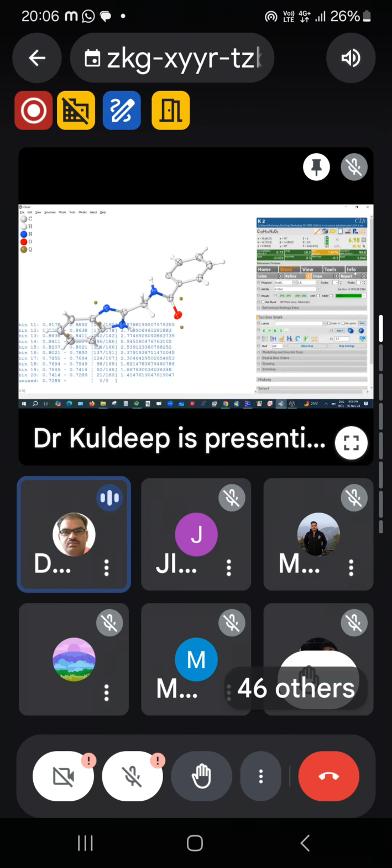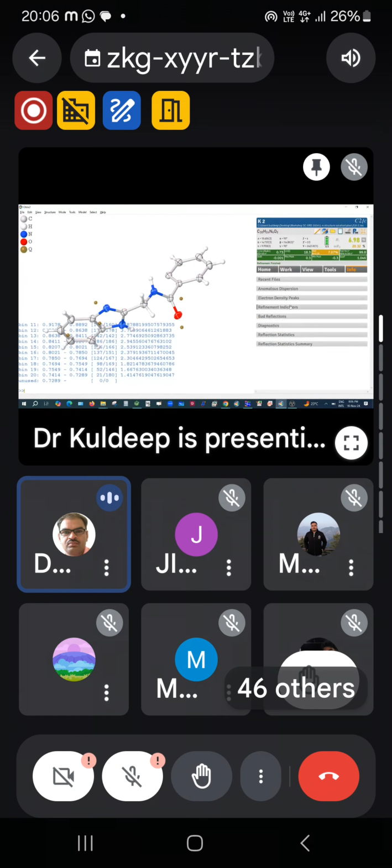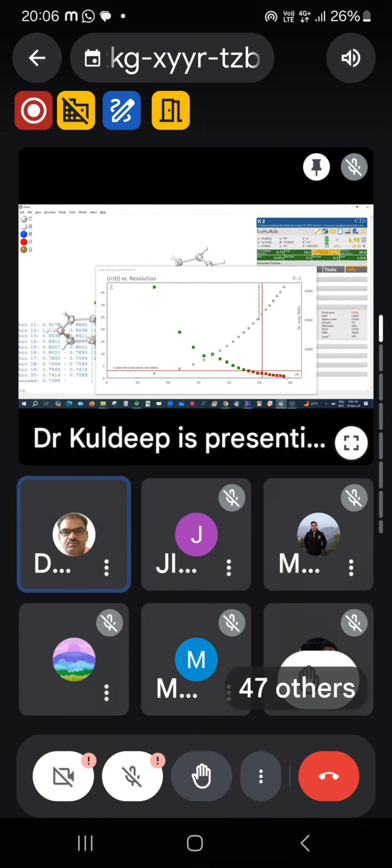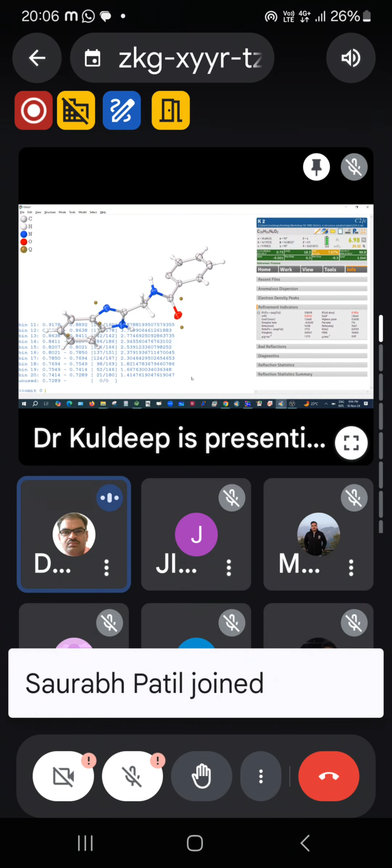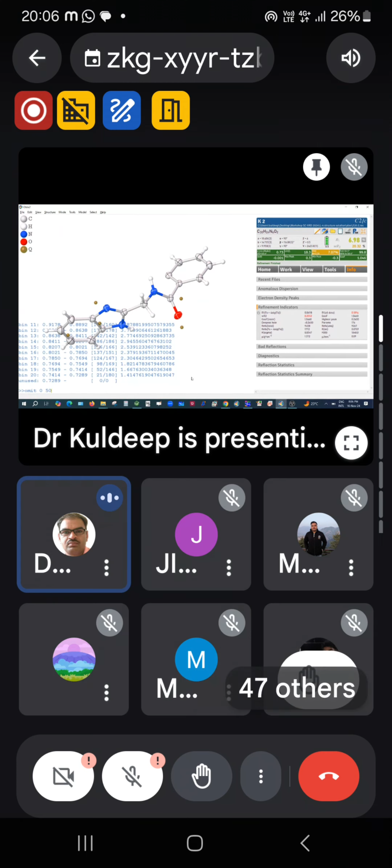Then you can see, okay, then info, there are some refinement indicators. Yes, there is some red there because the crystal quality is not looking so nice. So I think there is no meaning to keep the data at, suppose, 57 degree. We can cut the data at 50 degree, just typing OMIT 0, 50, because 50 is the minimum limit. You cannot go below this. Sometimes in special circumstances, you can go up to 48, 46 also, but you have to mention the reason why.